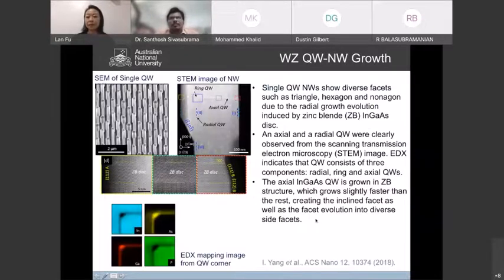It sounds very easy, but when we insert a few nanometers of indium gallium arsenide into our nanowire structure, what we see is a very non-uniform shape. You might remember the beautiful hexagonal, regular nanowire array we grew from indium phosphide. But this image shows that when we switch in a very thin layer of indium gallium arsenide, the whole nanowire morphology has changed. This really depends on the formation of indium gallium arsenide.